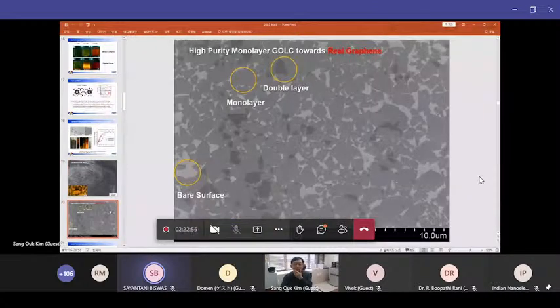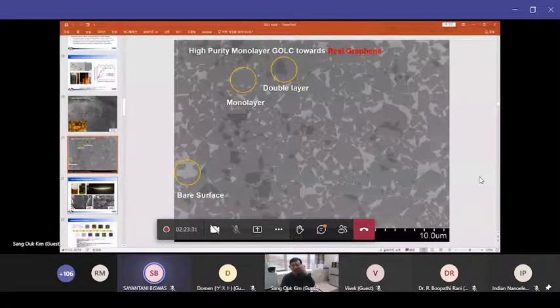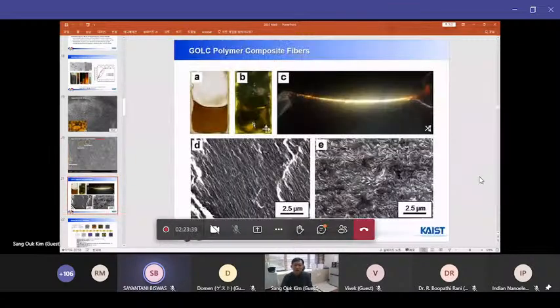And after our careful verification, we could get almost 100% monolayer exfoliated graphene oxide. That's why we can get very interesting liquid crystalline properties even for a relatively low concentration dispersion in water. And all this monolayer exfoliated graphene oxide can be carefully reduced to make a high quality, minimally stacked graphene powder material, as I will introduce later. Actually, for this liquid crystalline state in water dispersion, you can also incorporate a water-soluble polymer to have a three-component liquid crystalline system. Based on this polymer-based gel structure, you can get a fiber structure by wet spinning. And after drying, based on the liquid crystalline property, all the graphene platelets are highly oriented in the fiber axis direction.